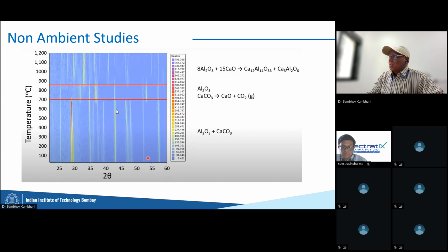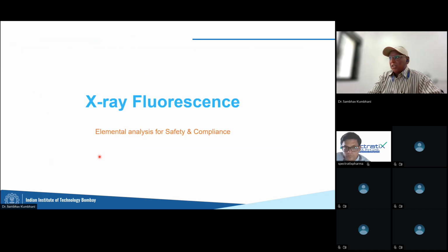Sorry. After 900, aluminum oxide starts reacting with calcium oxide and forms a completely new material, and it has its own set of peaks. If I had continued measuring, I could have found which peaks here represent this, and which peaks over here represent this. That can be done as well, or we can compare to reference spectra. That is also possible. So this is how you can do multi-material studies in a single plot. So that's all about XRD.